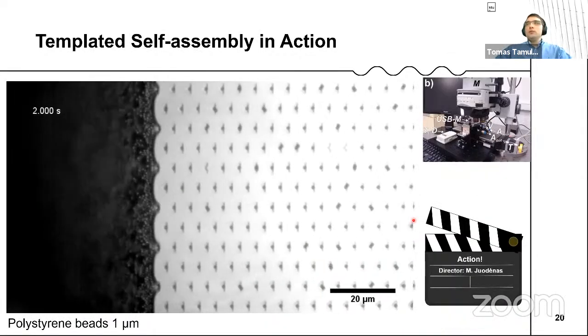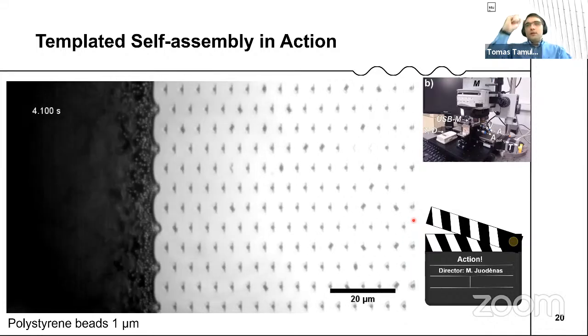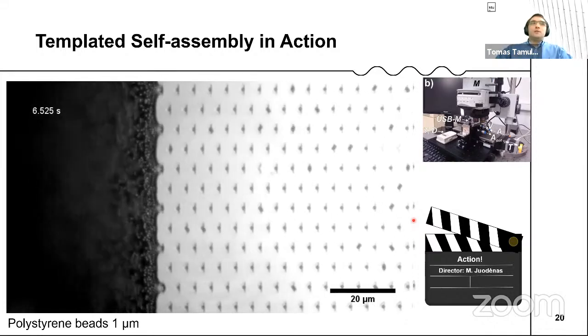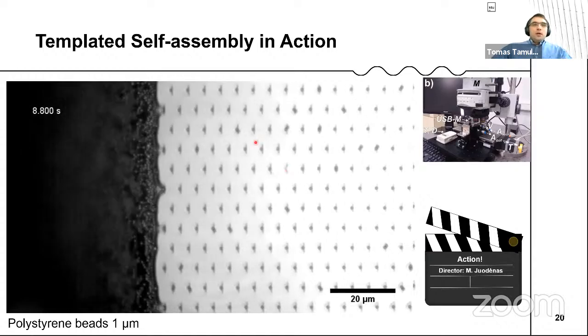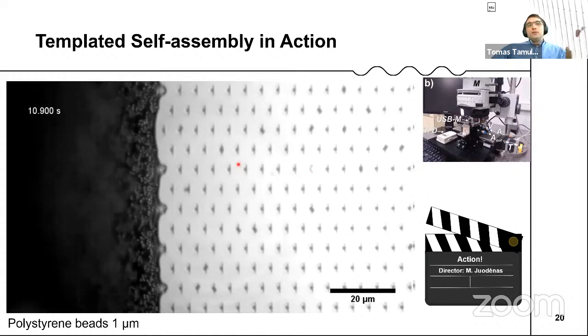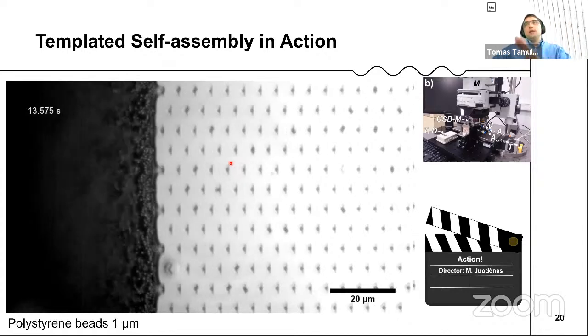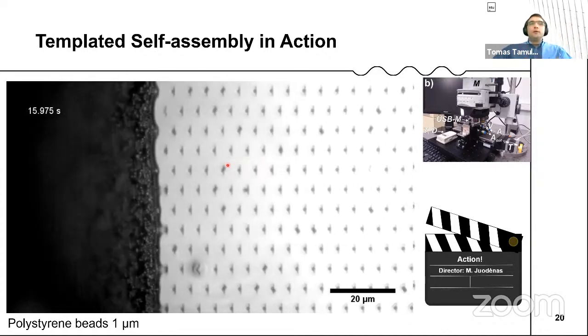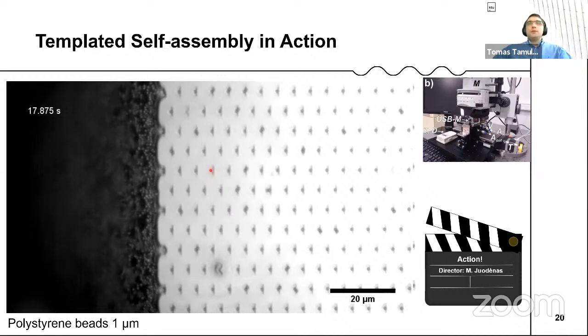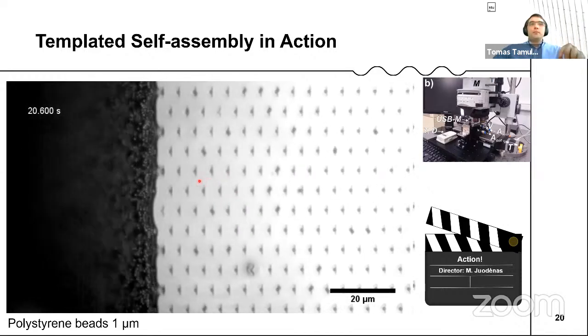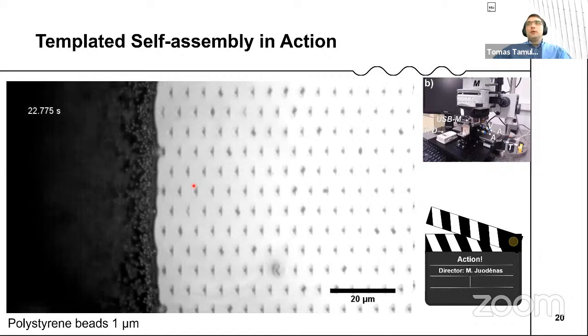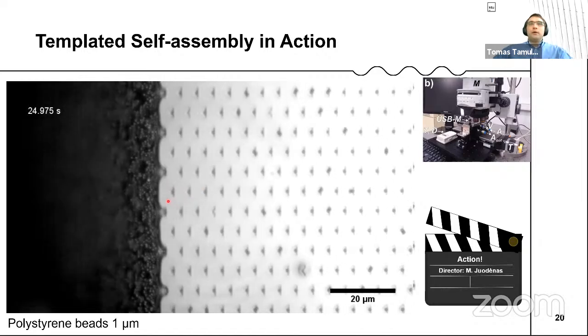And here is a nano movie made by a director, Dr. Mindaugas Juodėnas from our team. In this nano movie, you can see this substrate is slowly translated by some micrometer or below per second. We have these V-shaped obstacles that are able to trap, in this case, polystyrene beads, because you can see them through the microscope. So this is the microscope, this is the translation stage, and the process is happening in here. The cameraman is on top in this case.